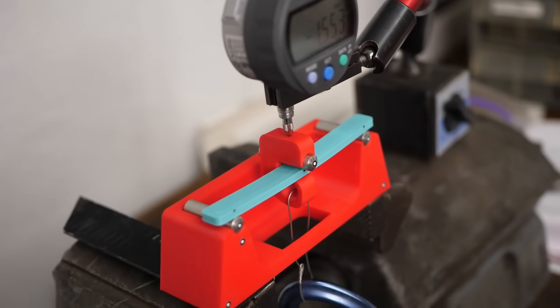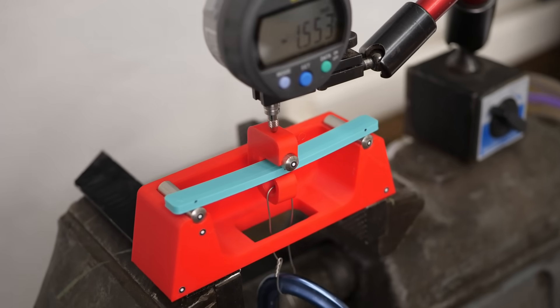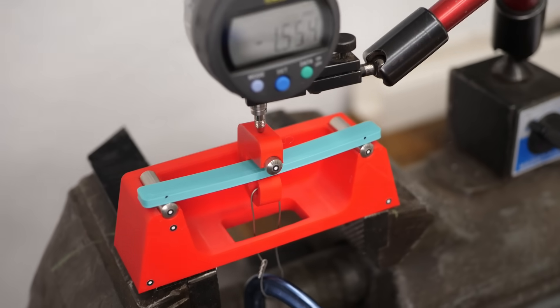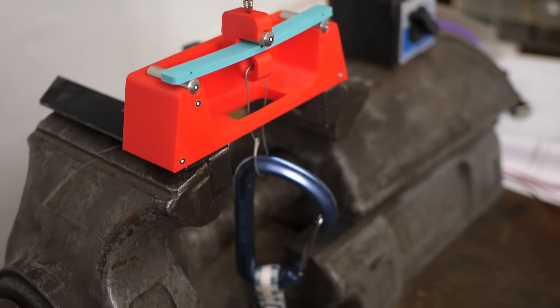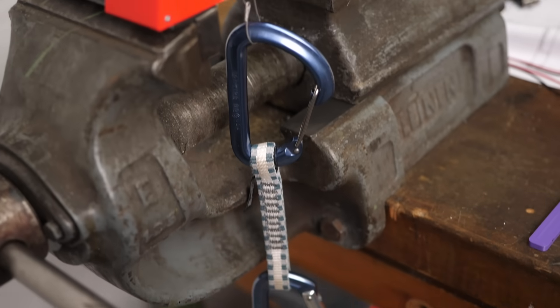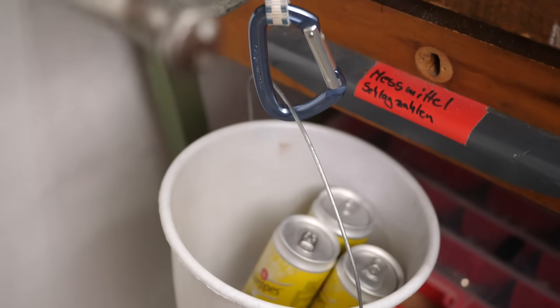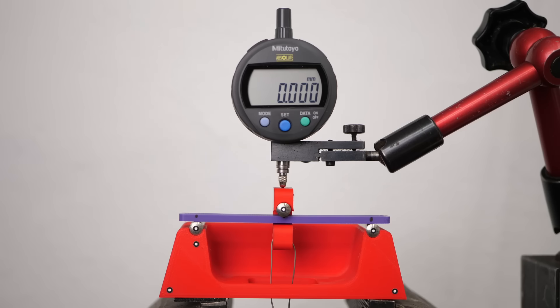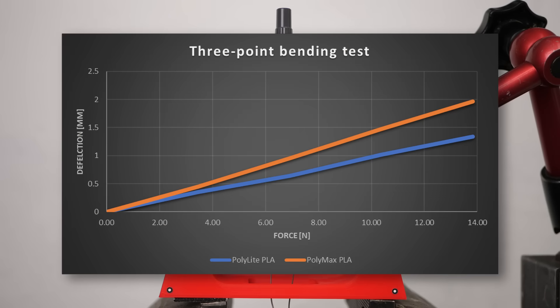Since the parts only from handling felt a little different, I also tested them for stiffness using a 3-point bending rig. So I loaded printed bars with increasing weights and recorded the deformation. It was clearly visible that the modified PLA deformed more under the same weight as regular PLA.